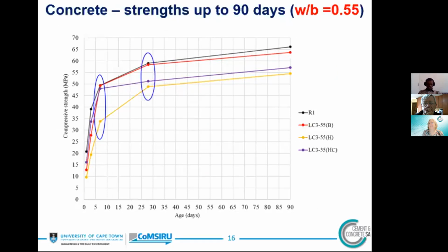At 28 and 90 days, the strength of the 55 mix with B clay is close to the reference mix. And you can see the 55 mix with H clay again has the lowest strength at all ages. The yellow line.